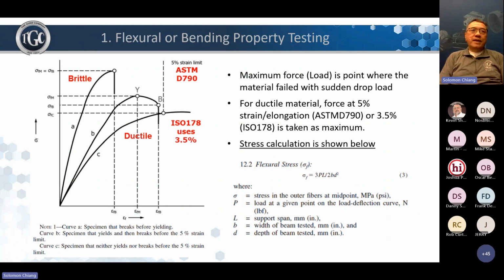And for brittle material, the fail point is where the material fails, and the UTM will pick up a fail point. For ductile material, because it doesn't fail, then ISO or IEC say stop it at 3.5%, and ASTM says stop it at 5%. And in that zone, it really doesn't make a lot of difference whether it's 3.5 to 5% elongation. Essentially, they just want to have a standard where we stop the testing.